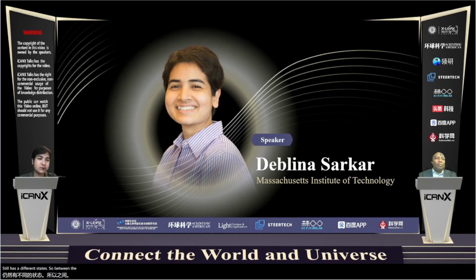So between the 3D and the 2D material, there are defects, and so we have to passivate the 3D material for the 3D to 2D material interface. But what is good is that between the 2D material and the gate dielectric, the interface can be relatively pristine, so the electrostatics can be much better. And yeah, if there are defect states, that can kill the tunneling.